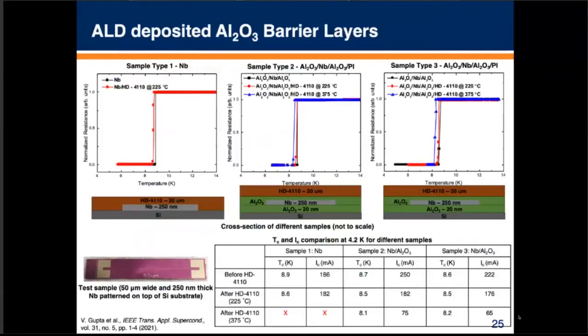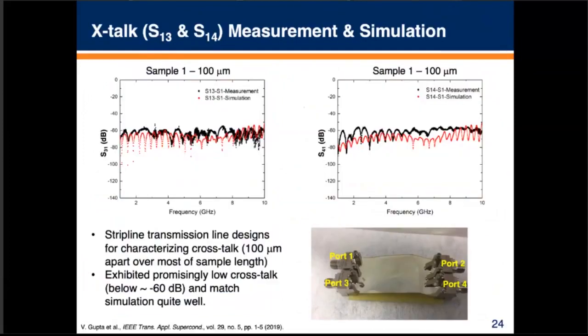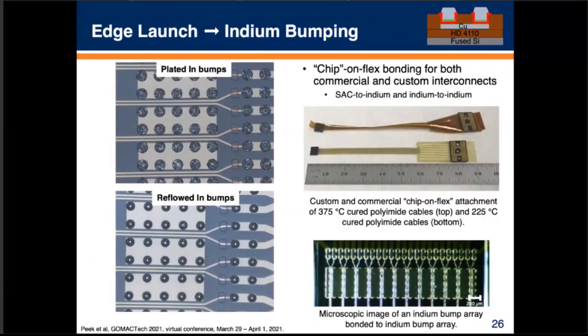If I go back here, you can see we're still using edge launches in these samples, but that's not really the route to a high density of interconnections. So we've moved to an indium bump process, and this shows how that looks for the plated bumps and then reflowed. This is what one of the more recent versions of the cables looks like, depending on some curing approaches. Sometimes if we don't do it right or we use the wrong stack up, we get some curling of the polyimide, but if we do it right, we can get nice flat polyimide.